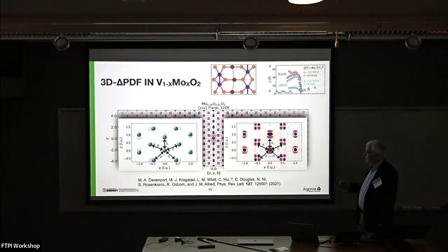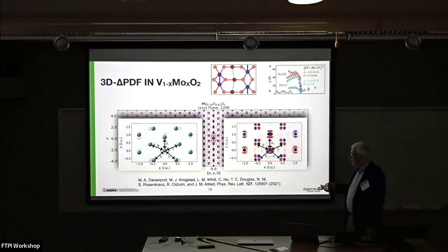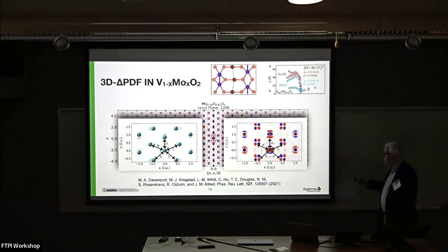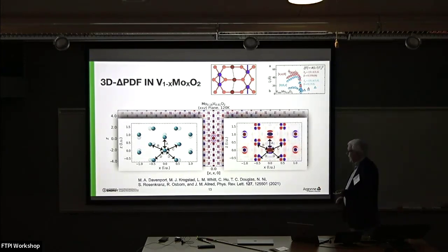And so you can see here, this is the crystallographic structure for what you get for an M2 phase. Here are two dimerized vanadium ions, and here you can see the buckled chain next to it. And indeed, we see exactly those interatomic vectors. We should see a shortened vector here, along the z-axis, and we see this extra buckling of the vectors along this direction. And you might argue that I'm missing this position here, and that's because we're summing over all of the possible sites in the system, so we have to consider other vectors.